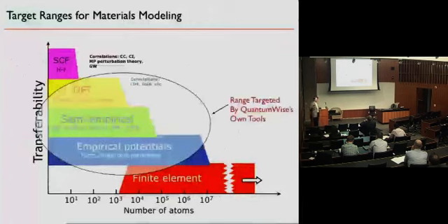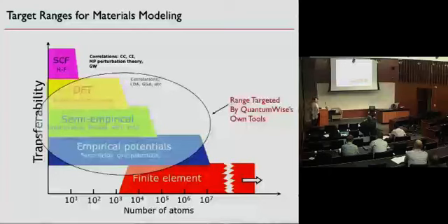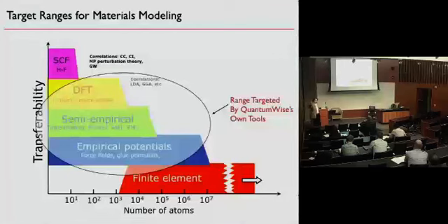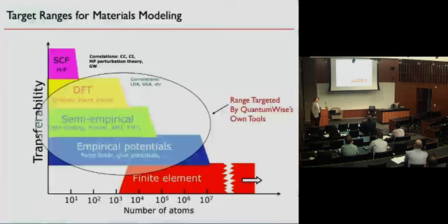In practice, you're not done if you can do quantum mechanical modeling, because you want to go to relatively large scales, even for what we can do. Even if you're at the scale of 10 nanometers or 20 nanometers, this is not done with just 1,000 atoms in your model. So what they try to do is cover a whole hierarchy of methods in their utilities. And this is here plotted as the number of atoms versus the applicability of the method. So for these high-end methods, they're rather general, like Schrödinger's equation, which you can essentially apply to any element, and if you do it right, you would get the right answer. You can't do that for 10 to the 6, 10 to the 7 atoms. There you need to have something that's very specific to your model, so you need to parameterize very well to get out what you hope to get out.